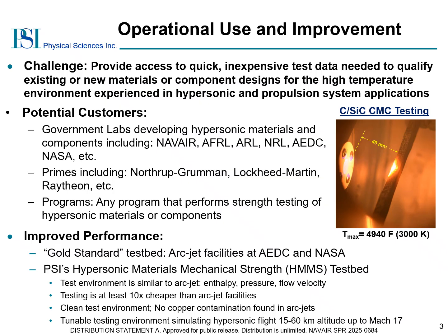By controlling the test enthalpy, determined by the ratio of coupled microwave power and the source gas flow rate, typically air, and the test pressure, the hypersonic materials testbed provides a tunable test environment encompassing Mach numbers ranging from 2 to 17 at simulated altitudes from 15 to 60 kilometers.